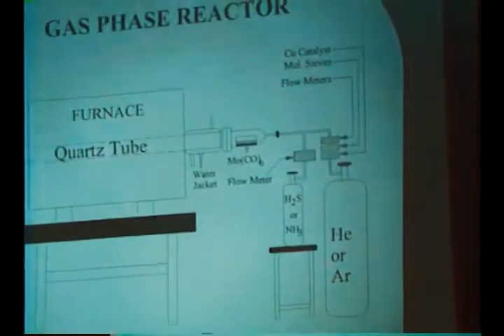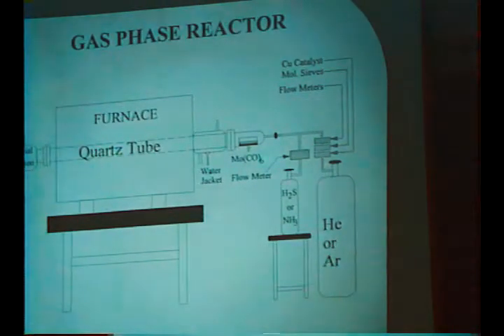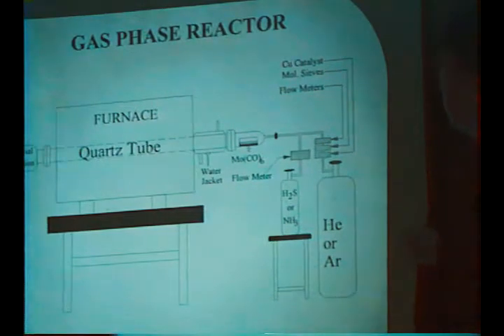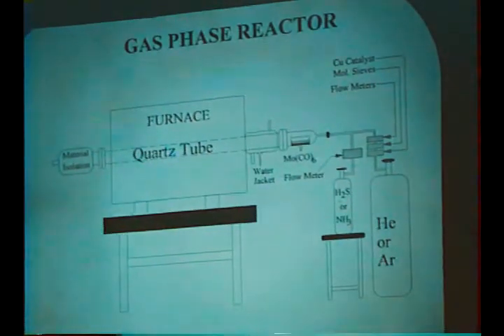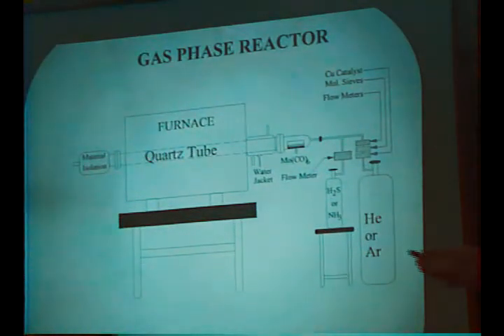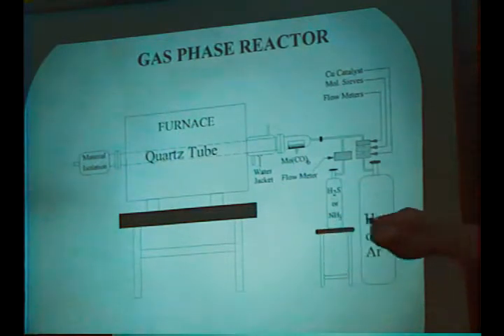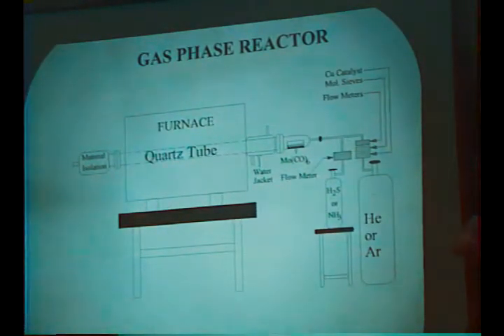This is a simplistic view of the gas phase reactor. I think it illustrates the important components of the reactor. First of all, we have helium or some inert gas or argon that is deoxygenated, dehydrated prior to running. Then we can use hydrogen sulfide or ammonia as the reactive gas. Both gases can be metered appropriately so that the stoichiometries can be controlled. The gases flow over the molybdenum carbonyl, which can be heated at a variety of temperatures, depending upon our needs. This actually controls the vapor pressure of the carbonyl. The carbonyl then is transported into a hot zone, ranging from 300 to 1100 degrees centigrade. The material passes through and is collected.